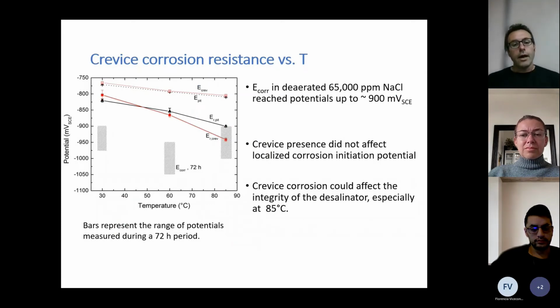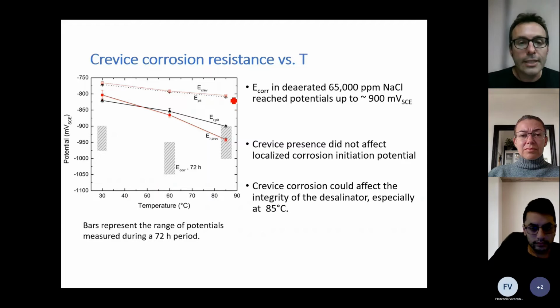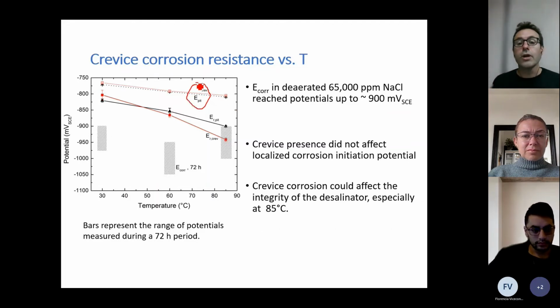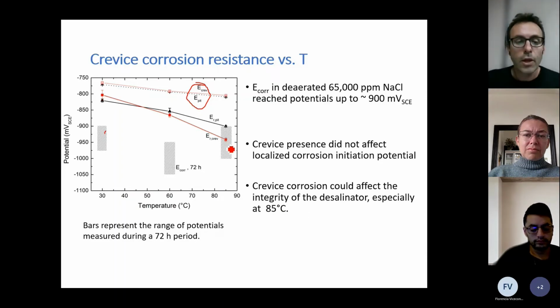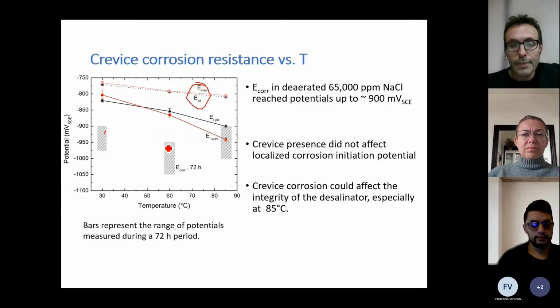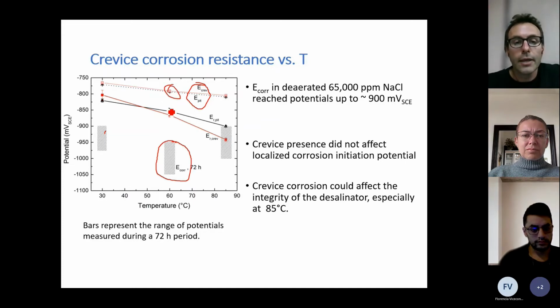So in terms now of summing up all our results on crevice corrosion and pitting corrosion resistance versus temperature, what we see here is that pit initiation and crevice initiation potentials are very similar and both of them decrease with temperature. Repassivation potentials occur at lower potential than initiation, and the hatch band here, those rectangles, represent the range of open circuit potentials measured during the 72 hour period. So a common rule for predicting crevice corrosion or pitting corrosion is to compare your open circuit potential, which is here, with the critical potentials for initiation and repassivation.